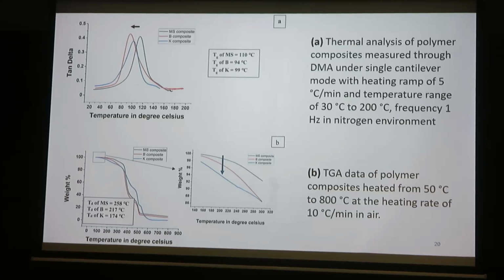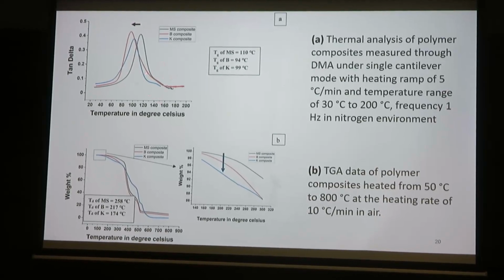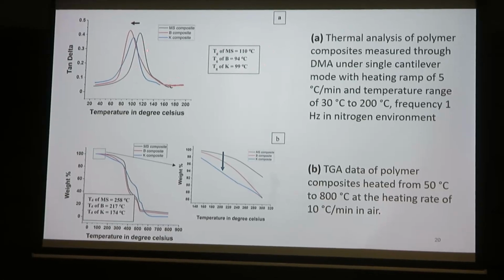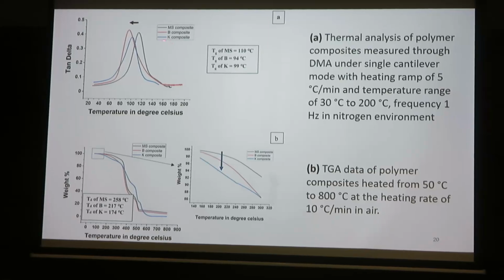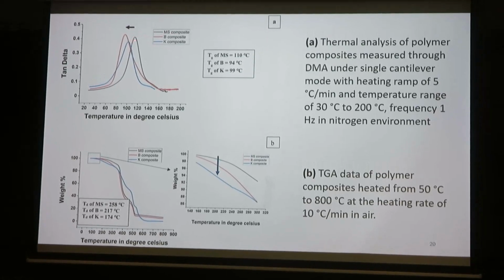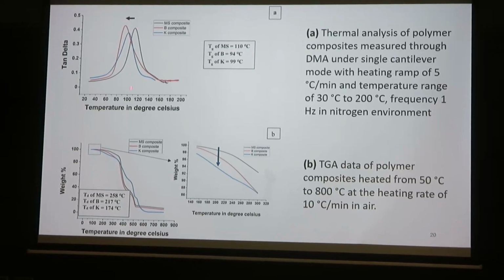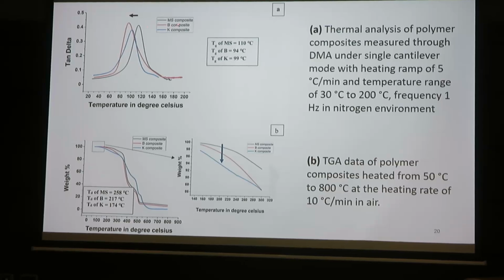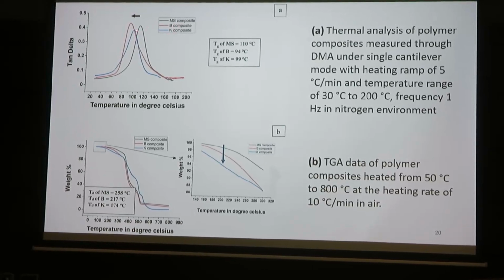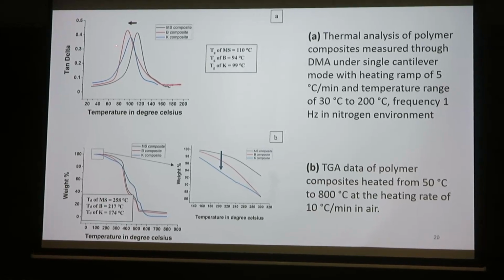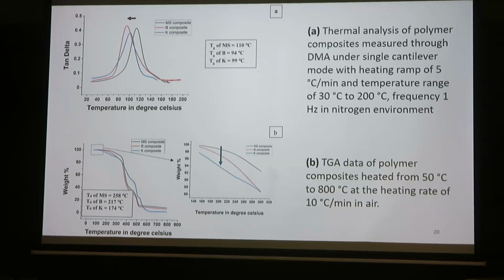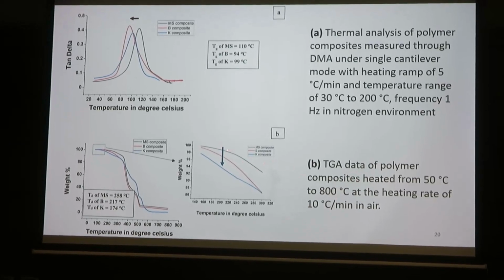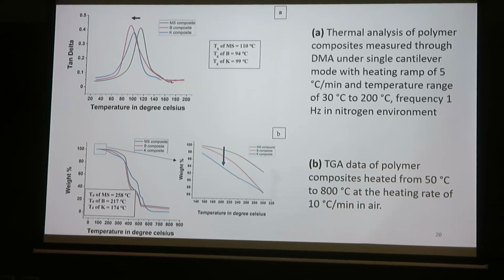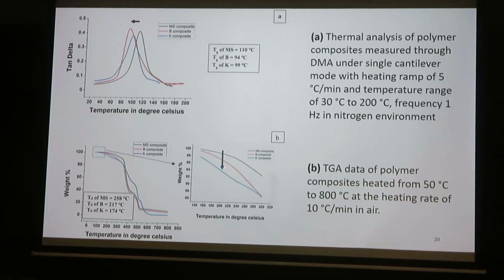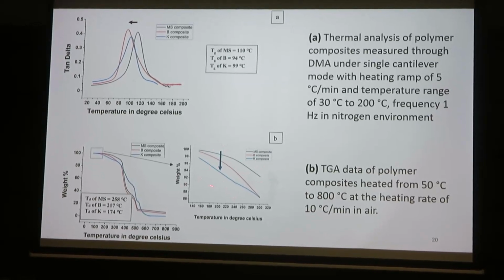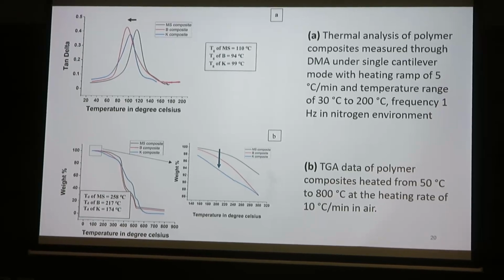And some other properties, for example, thermal properties and Tg. So, as I said, Tg is also important for us to understand, but sometimes it may not have a direct correlation. So, for example, in this case, for the base polymer composite, we have got Tg in the range of 100, but for the other composites with oil and with Kevlar, the Tg is slightly lower. Okay? So that means it is behaving with a slightly brittle nature. And also TGA, where we find out the thermal stability, by adding the fiber or the oil inside, the thermal stability has gone down. Okay? But not necessarily that they will be affecting tribology in the same way.